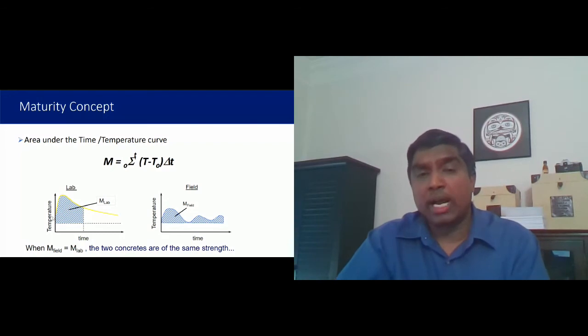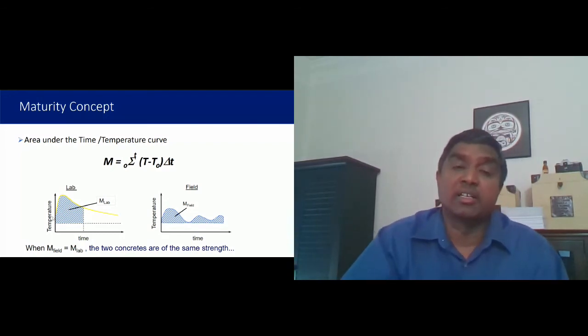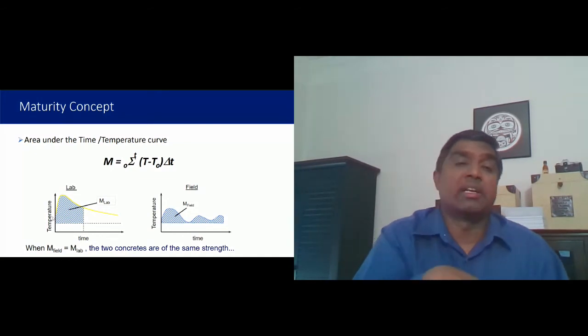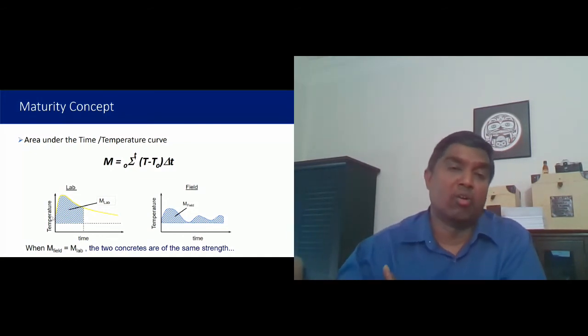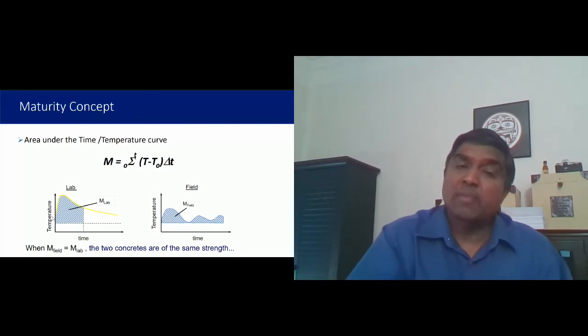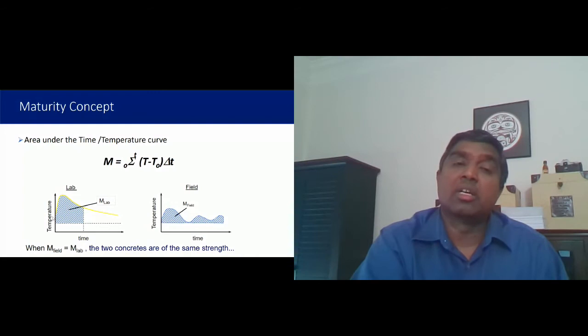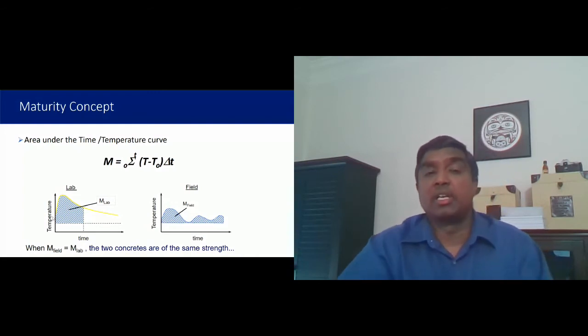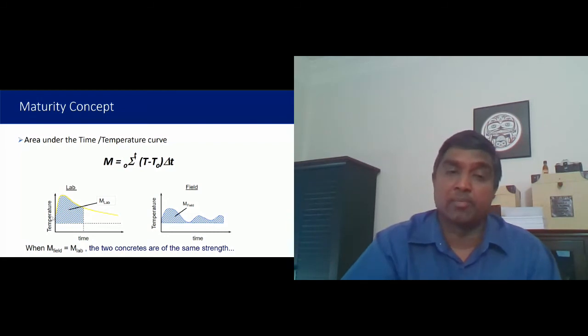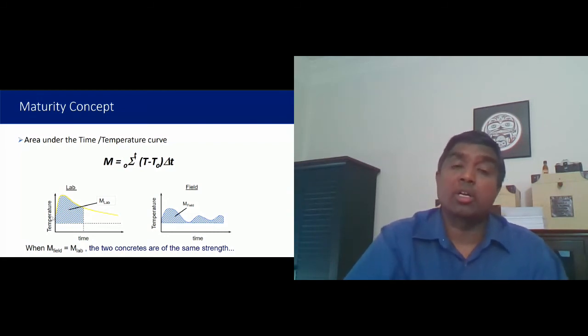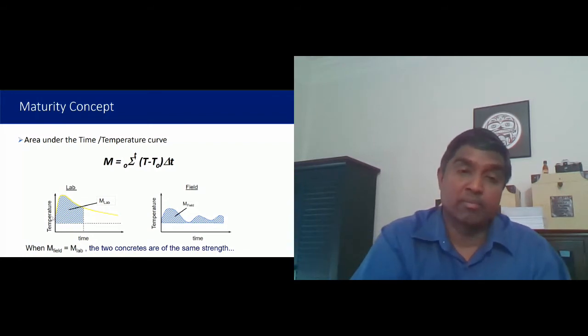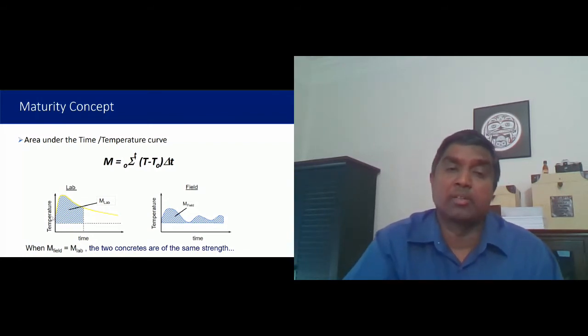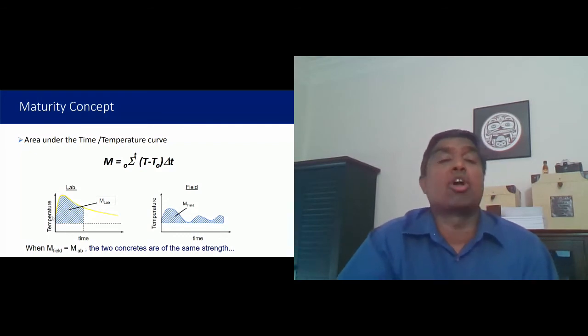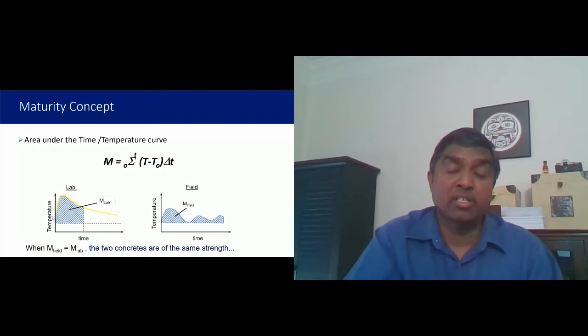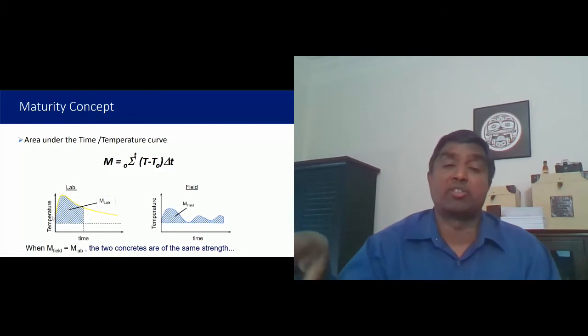Once we do that, we break the cylinders at different intervals of time, let's say at day 1, day 2, day 3, and it could be up to day 14. Each time we break the cylinders, we also measure the corresponding maturity number from the sensor in one of the cylinders that we placed. Using that information, we plot a curve between maturity and strength. As you can see on the left-hand bottom side, that curve is called the calibration curve. For a given mix, as long as the mixture proportions do not change, we can use this calibration curve for the rest of the project.